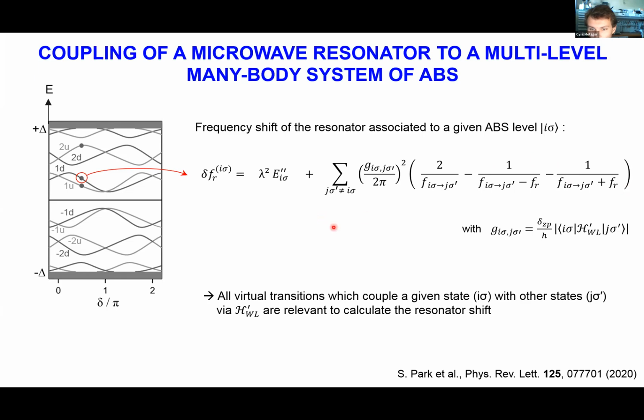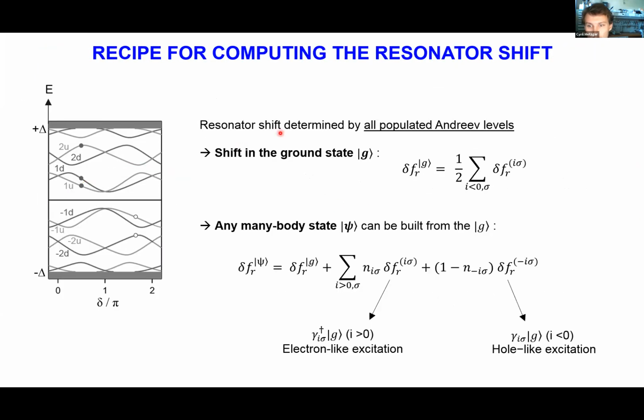So I'd like to stress here that despite the apparent simplicity of the equation, it can be actually quite tricky to implement it in practice when we have to deal with the multi-level nature of the Andreev spectrum in finite length junctions. Not to mention that in finite length junctions, the matrix elements as well, the g_ij, do not assume an analytical form. So how would you do it in practice? What's the recipe for computing the resonator shift?